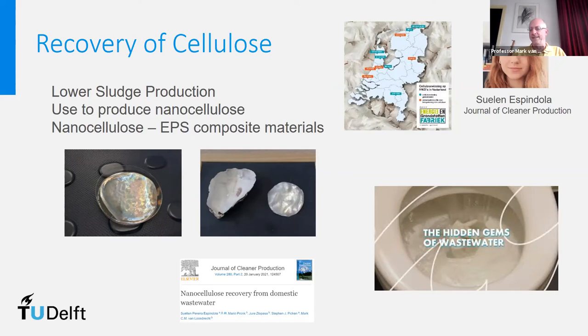But like with phosphate, the amount of phosphate or cellulose we recover at the treatment plant is relatively small compared to all what is used in industry. But cellulose, which is used in toilet paper, has one advantage because it's delignified. The lignins have been removed to make paper soft. And delignification is the first step to do in order to make nanocellulose. And so we are looking to recover it mainly as nanocellulose because it will be cost effective in the nanocellulose production because the delignification step is not needed anymore, which is relatively expensive.